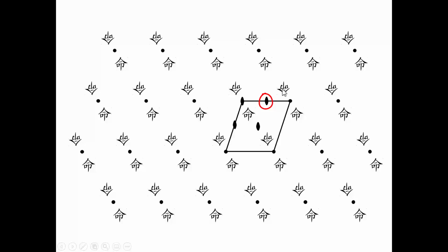here. I'm not going to draw them all in, but what we would see is that at every lattice point, there's a twofold rotation axis. And at the center of each edge, and then at the center of the parallelogram, that's a unit cell. So in this depiction, we can see the synergy between the translational symmetry and the point symmetry.